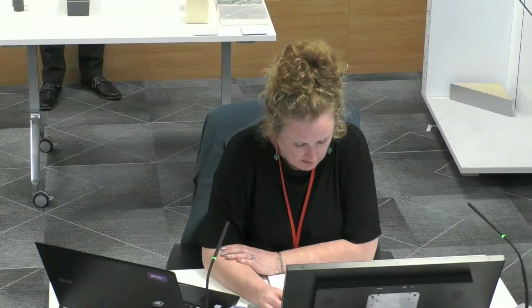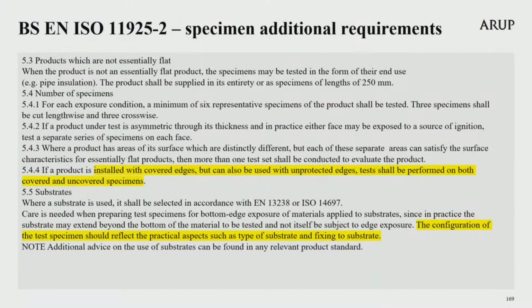As stated on the screen, a total of 6 representative specimens are required in one test. Another key point is if a product is installed with covered edges, but can also be used with unprotected edges, tests shall be performed on both covered and uncovered specimens. This is different to Part 6 and Part 7 discussed earlier, where the tests are designed to prevent edge exposure. Again, the issue of incorporating the influence of the substrate on the specimen behaviour is addressed clearly in the standard.